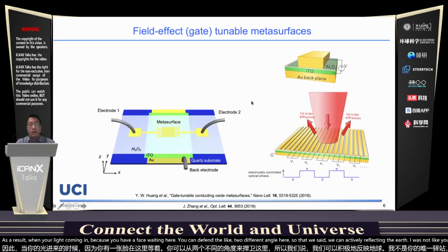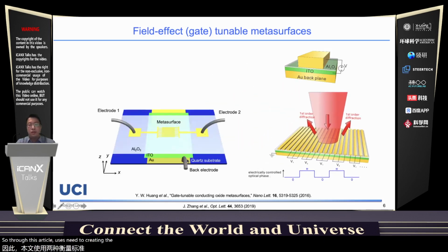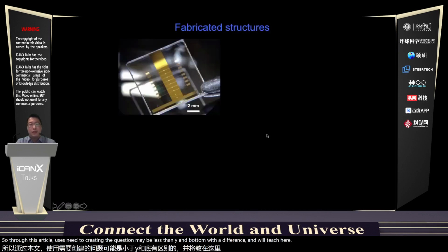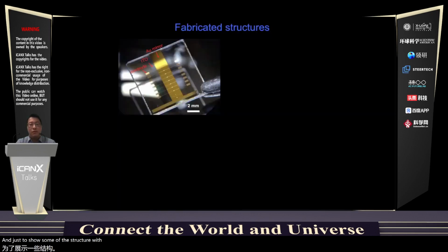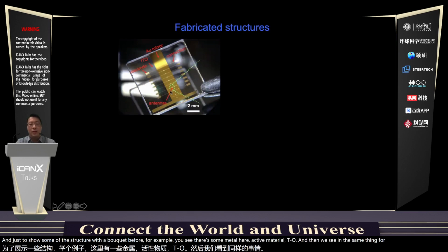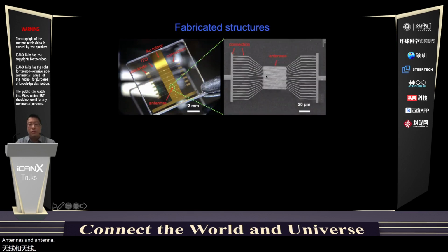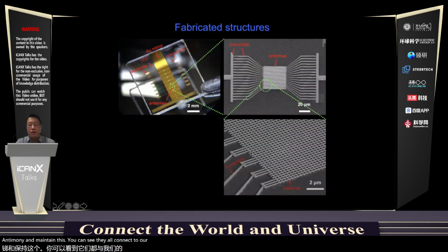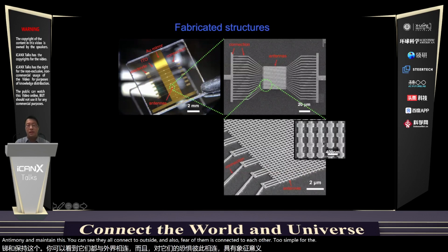To do this, basically you just need to gate the structure, maybe left and right and bottom, with a different voltage here. And just to show you some of the structures we fabricated before, you see there's some metal here, the active material ITO, and then in the center we have antennas. You can see they all connect to the outside, and also three of them are connected to each other. If you zoom in further, you see this kind of antenna is really small. We're talking about a few hundred nanometers in size here.